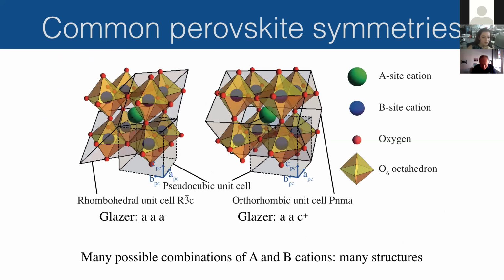So this is now just 2 examples of the types of primitive unit cells that you can get when you do these types of distortions. So this is a rhombohedral unit cell, this is an orthorhombic unit cell. They are both very common in perovskites, and there are subtle differences between them. Basically, you obtain these unit cells from the cubic unit cell by just rotating the oxygen octahedron. Now, there exists a very useful way of explaining how the octahedra are rotated, and this is called Glazer notation. So that is what I have written at the bottom here. So I will explain on the next slide how Glazer notation works. But basically it tells you how the octahedra are rotating, and that's the only difference between these 2 unit cells. So how do you get these different unit cells? Well, you just change the different cations and the structure changes as a result.